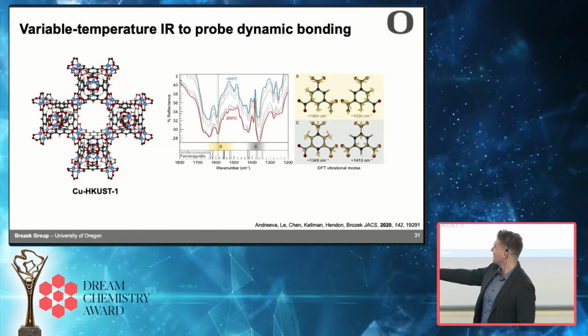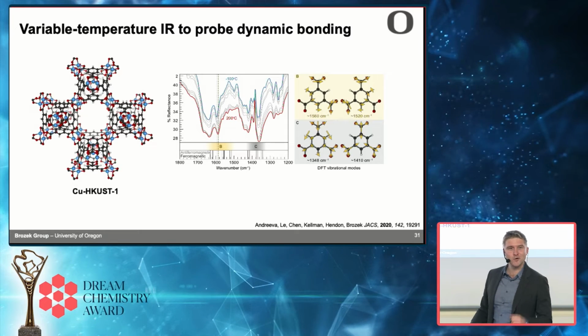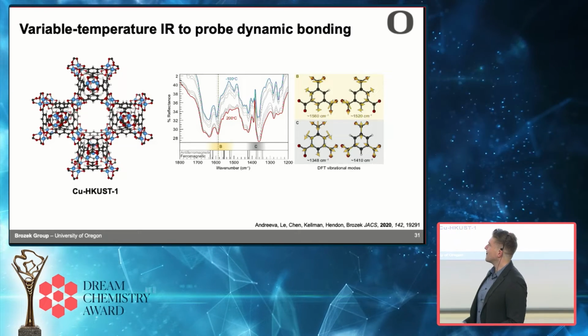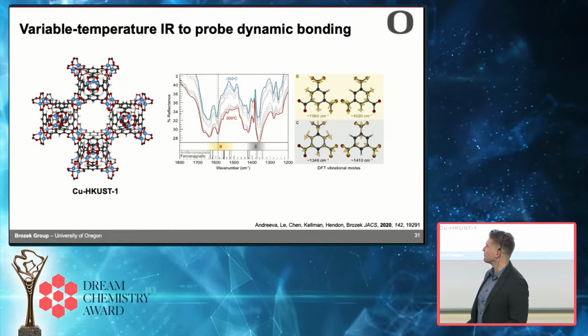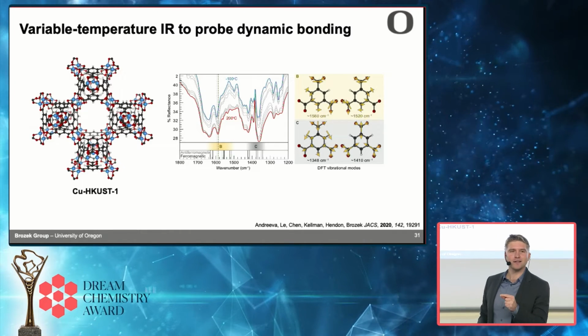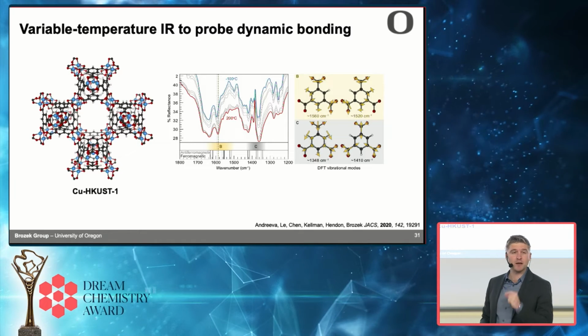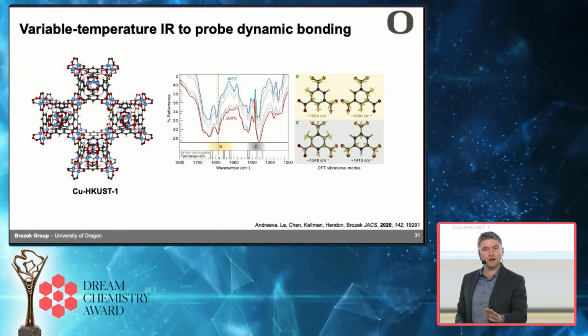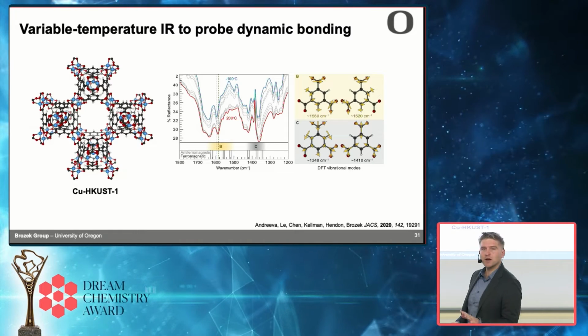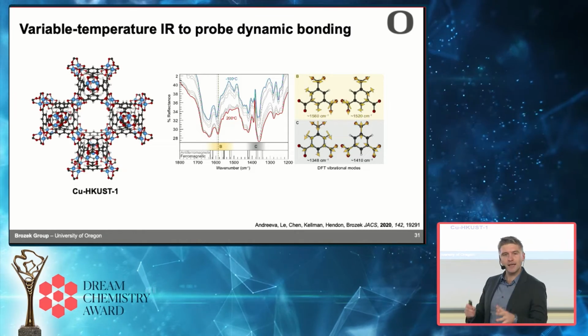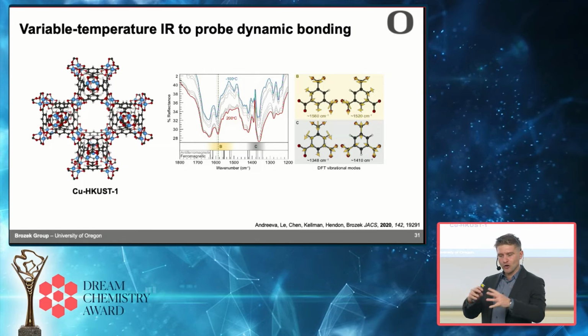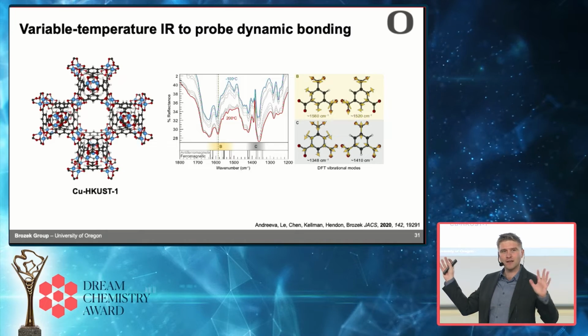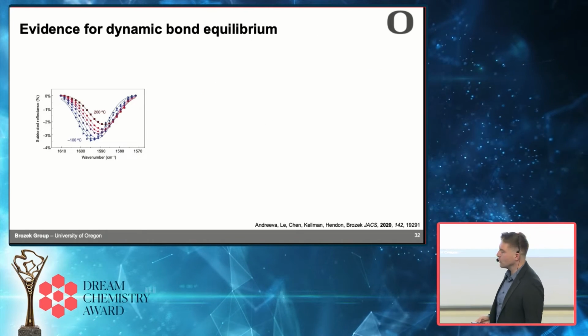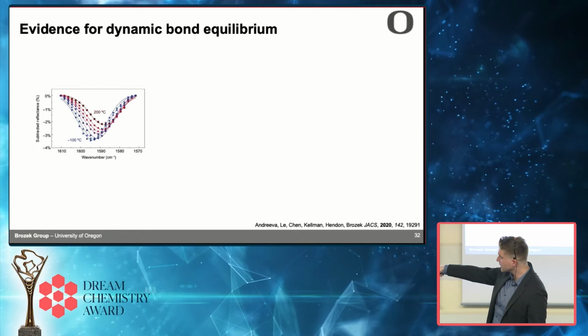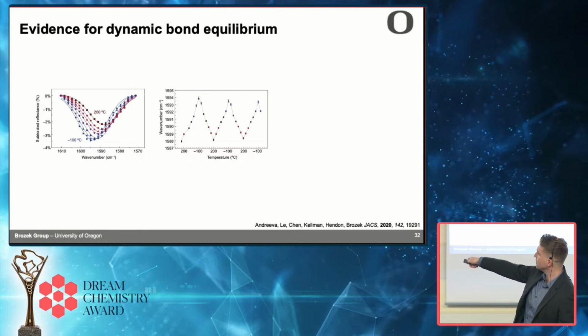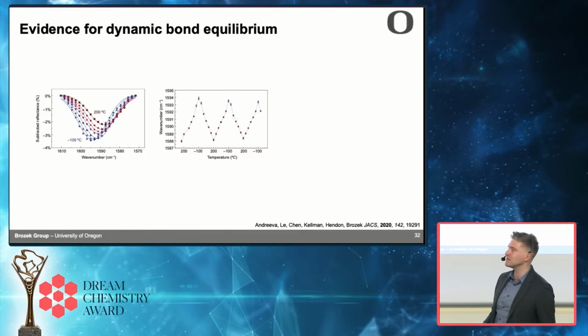And so I wanted to make sure I knew what the heck was going on here. So I worked with my excellent collaborator and colleague, Chris Hendon, who was a finalist here a couple years ago. And he helped us simulate the whole IR spectrum. And what we saw is that any band that redshifts has at least some carboxylate character. If a band has no carboxylate character, it doesn't redshift. And that's kind of special. That tells you that when you heat or cool a MOF, all of the changes are absorbed and localized in those metal carboxylate bonds. Nothing else seemed to be affected. We can look at that asymmetric stretch, and when we normalize the data, it is clearly redshifting. The effect is reversible, so we aren't just introducing defects, we're not just destroying the material.